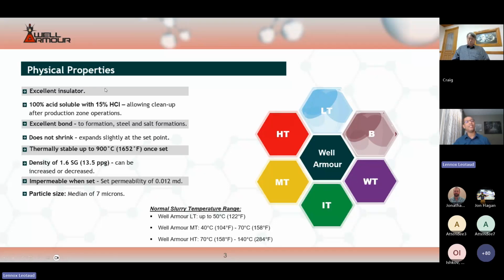To touch on some of the physical properties, once set, the Well Armour is an excellent insulator. It's also 100% acid soluble with 15% HCl, which is an important attribute or property. Let's just say you want to use the Well Armour as a temporary abandonment plug across a producing zone, for example. It does provide excellent bond both to steel and salt formations and in general any formation. It does not shrink, and in fact it slightly expands at the set point. The set material is thermally stable up to 900 degrees C, and the neat slurry density is 13.5 pounds per gallon. But that density can be adjusted if required or necessary for a particular job.